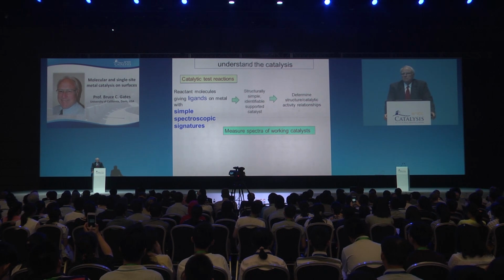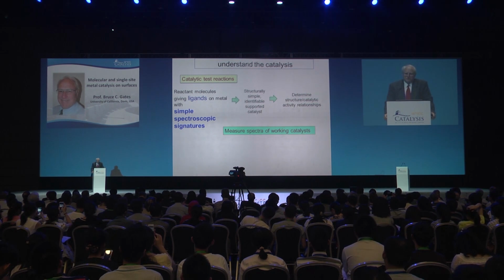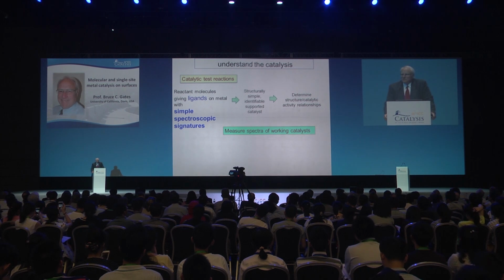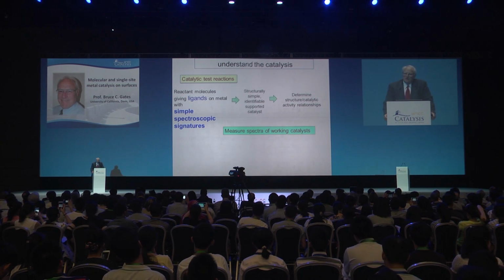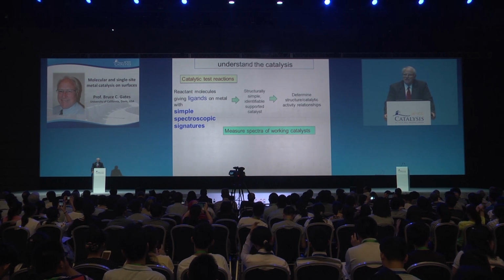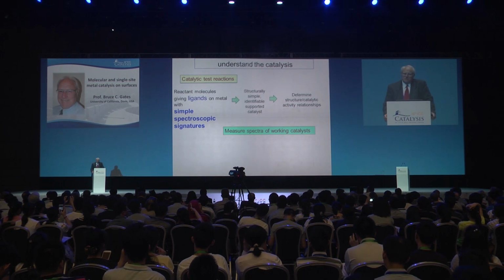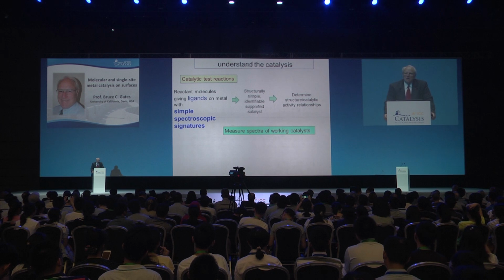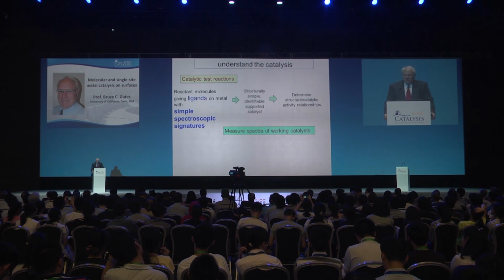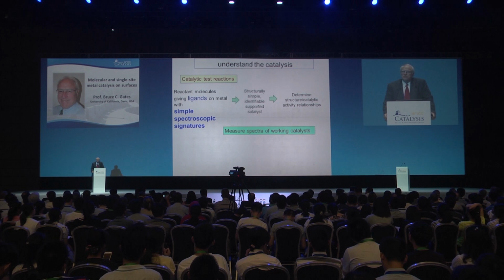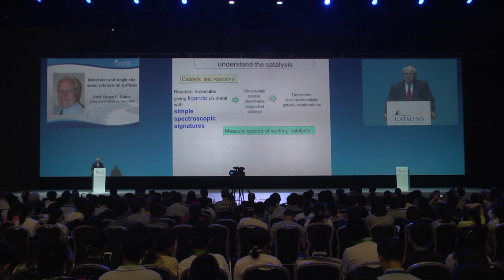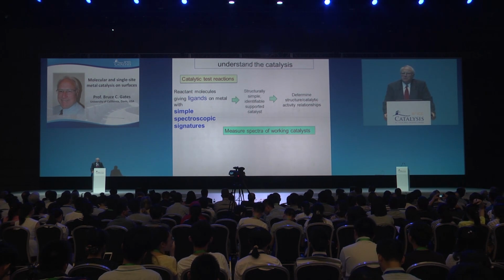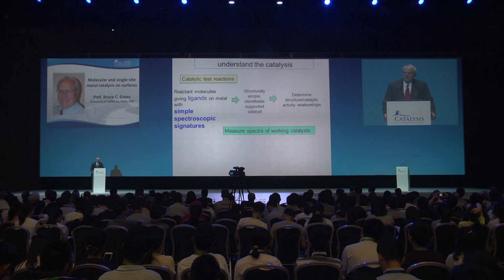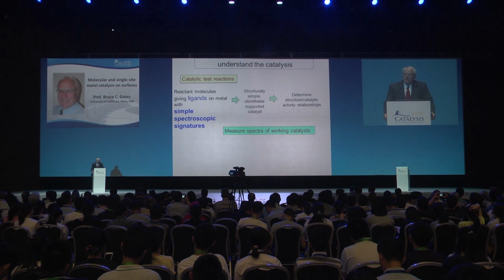As a catalytic test reaction, we'll use a simple one, on its face simple: ethylene conversion with hydrogen. It makes ethane and it makes butenes. It's an oligomerization as well as hydrogenation. We choose this simple test reaction because it occurs under mild conditions and the catalyst is stable. But more important, the reactants form ligands that provide signatures in the spectra that help us understand what the catalyst is and what it is in the functioning state.